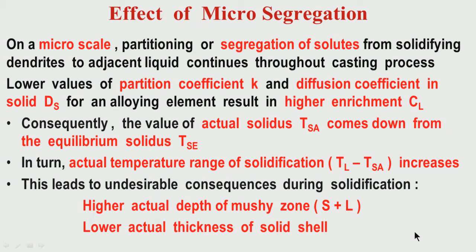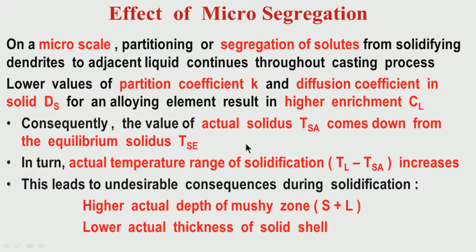First, the last portion of the solid which is forming is very rich in alloying elements compared to the earlier portion of the solid. So, the central portion of a cast material is always more rich in alloying elements, more rich in solutes, number 1. Because of segregation, which is an important consequence of solidification, there will be segregation.